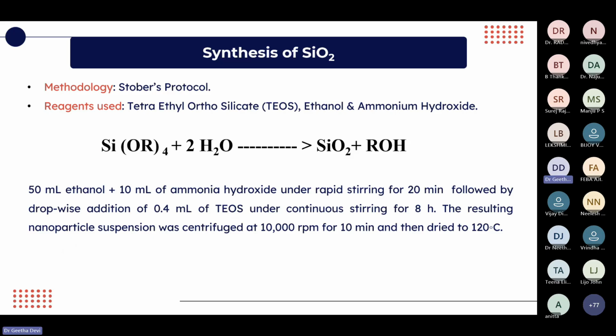The synthesis of silica nanoparticles. The nanoparticles are synthesized using Stöber's protocol by reacting tetraethyl orthosilicate, ethanol, and ammonium hydroxide. So the reaction is shown here.